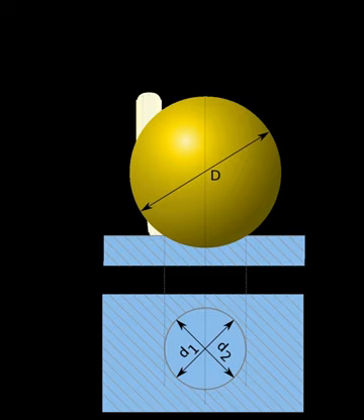The BHN can be converted into the ultimate tensile strength, although the relationship is dependent on the material and therefore determined empirically. The relationship is based on Meyer's Index from Meyer's Law. If Meyer's Index is less than 2.2, then the ratio of UTS to BHN is 0.36.